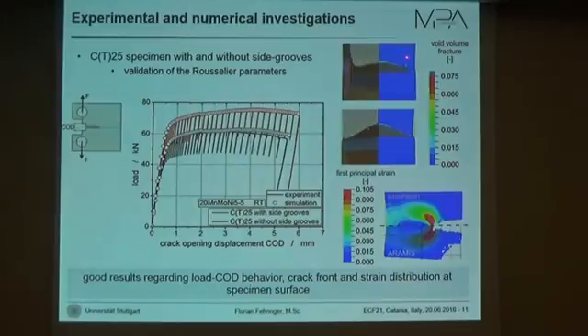What we also can do is simulate the crack front of the specimen. You can see the crack front at the end of the experiment for the experimental side and the numerical side, and they fit also quite well. And the same for the strain distribution on the surface of the non-side-grooved CT25 specimen. So all in all, we have good results regarding the load COD behavior, the crack front, and the strain distribution.